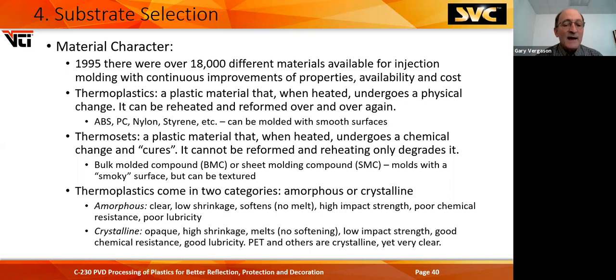Thermoplastics can be ABS, polycarbonate, nylon, styrene, and the list goes on. Your thermosets, BMC, which is bulk molding compound, or SMC, sheet molding compound, can be molded. The surface is kind of smoky. It's a little rough, and your coating's going to look rough as well. Many of these materials have to be paint base coated in order to put PVD on top.